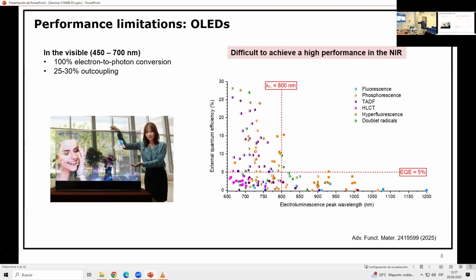into air. That's for visible light emitting, and here you see the state of the art if you go to infrared OLEDs, or near infrared OLEDs. Those are interesting for all the biosensing and so on, because your body is transparent in that range, not so much in the visible. So people are doing materials development for infrared OLEDs, and you see it goes down fast. And so the 30% which we have in the visible at 650, that's just dark red. And then if you go to the infrared, apparently it's not possible, or people haven't found the right infrared emitter yet, and there's several systems. So that's something at least our chemists are working on hard to try to get it a bit higher, around 800. That would be interesting, or 900, or even further. So that's a bit what the problem is with OLEDs, and there's other research you can do there, but that's what we are for.